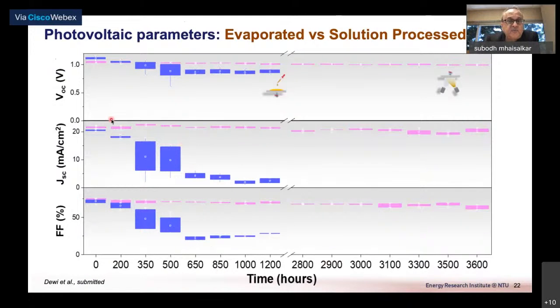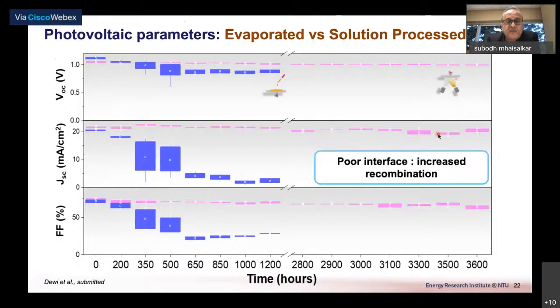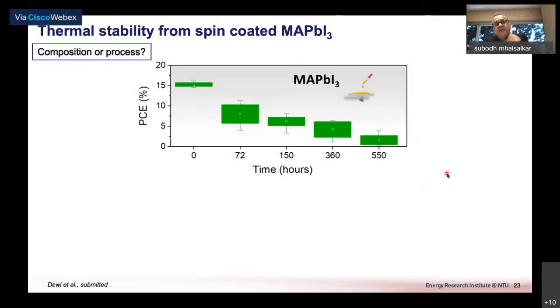And here I'm showing you the performance of methyl ammonium lead iodide and comparing it with the equivalent performance of the evaporated perovskite solar cells. One of the main reasons that we believe the stability of the solution process device degrades is because of interfacial issues. From the analysis that we have done, we see increased recombination, and that is the main cause of degradation of methyl ammonium lead iodide.